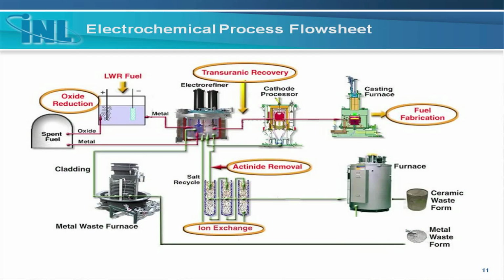This is a very simple cartoon view of the flow sheet for pyrochemical processing. And this one actually puts up the option of oxide fuel. Let me explain the oxide fuel side. Like I say, this process can be modified with head-end operations to take light water reactor oxide fuel, so it's UO2, plutonium dioxide, and fission product oxides. It can be taken to electrochemically reduce that oxide material to a metal state. So reduce the uranium to uranium metal, the plutonium to plutonium metal, and then that material can feed into the standard electrochemical process flow sheet.